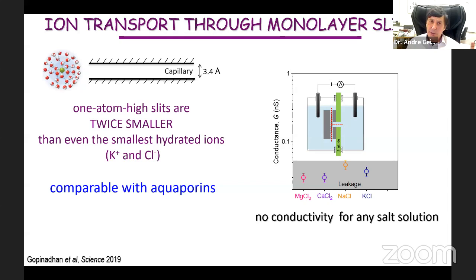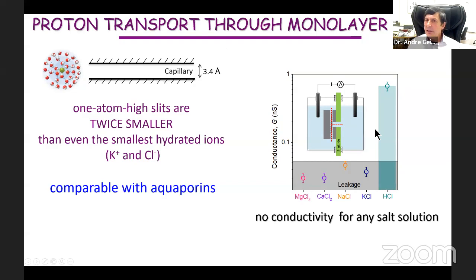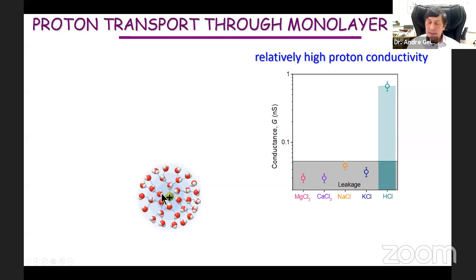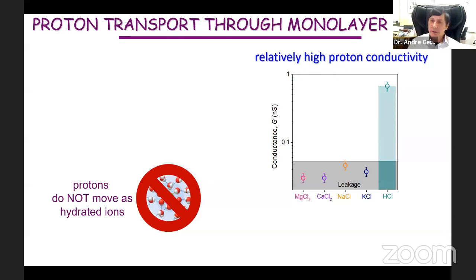This is essentially what we expect because the ion is much bigger than the channel width. It no longer has the possibility to compress, to be so flat, to go through this capillary. But then we surprisingly found that when you are talking about hydrochloric acid, it does go through. We see the conductance, and obviously because chlorine is the same, in this case it is hydrogen ions which go through. And this is kind of understandable because usually cations are covered with hydration shells, and that's what makes them really big. But for the case of protons or hydrogen ions, it's not the case.